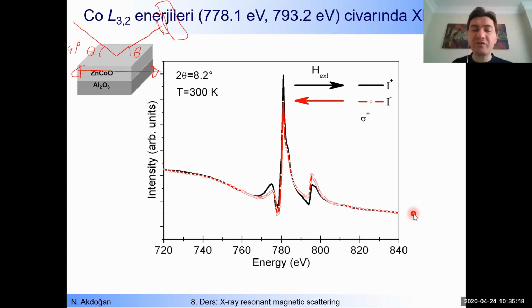Here I will show you the asymmetry ratio, but before I go to it, I would like to shortly touch another information. What you see here, the intensity for that energy is much higher than the intensity recorded for that energy. So what is the reason for that? If you apply magnetic field to the right side, we have higher intensity than the XRMS signal measured for the opposite magnetic field. But for that energy, the intensity for the opposite magnetic field is higher than the magnetic field applied to the right side.